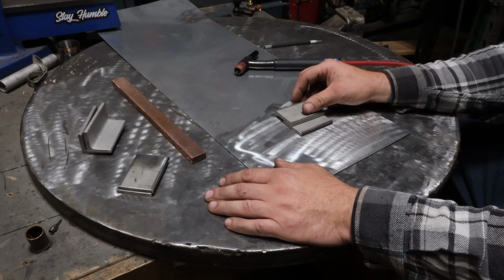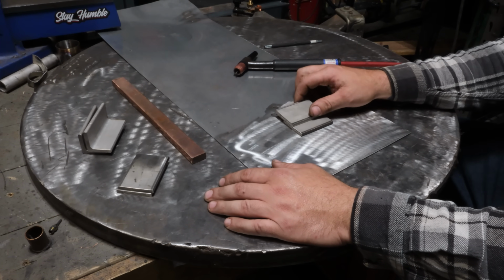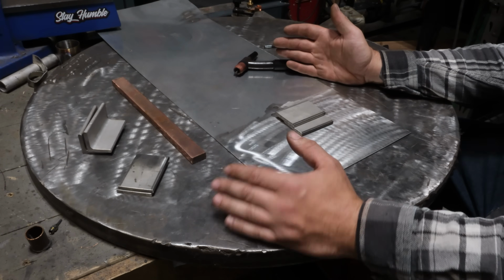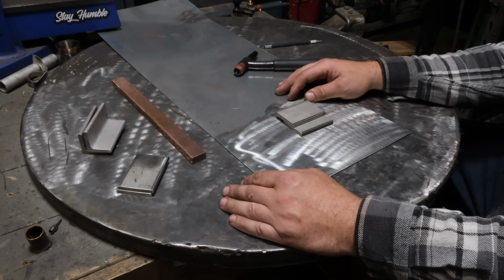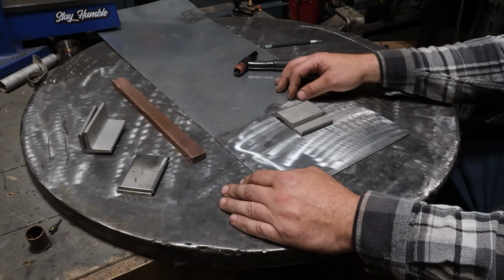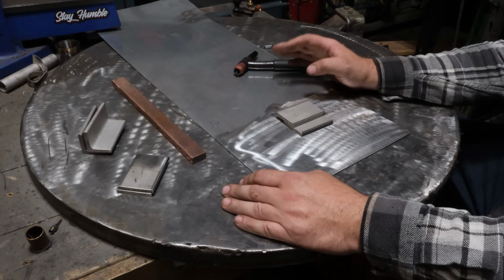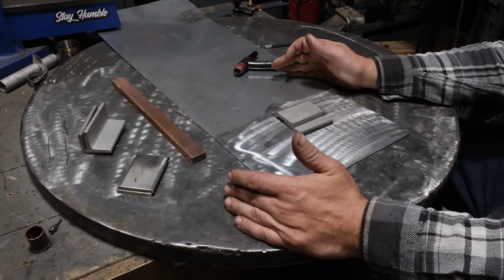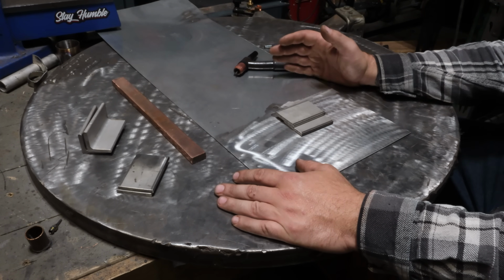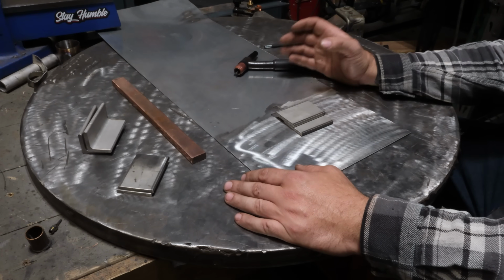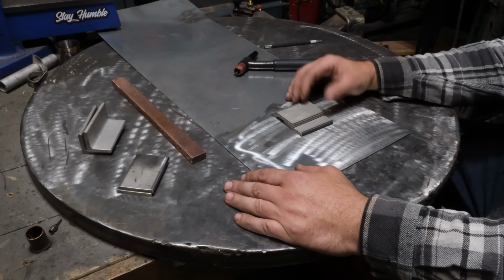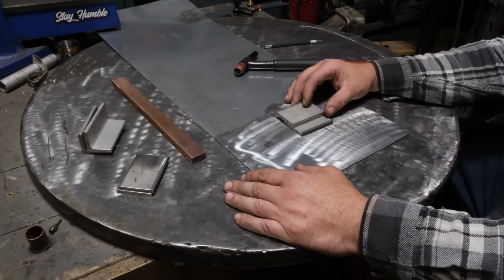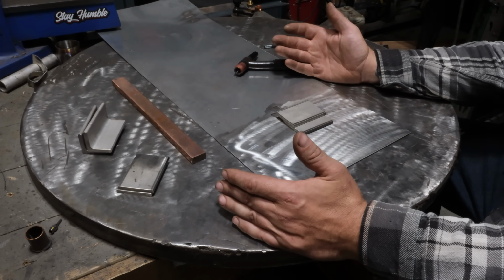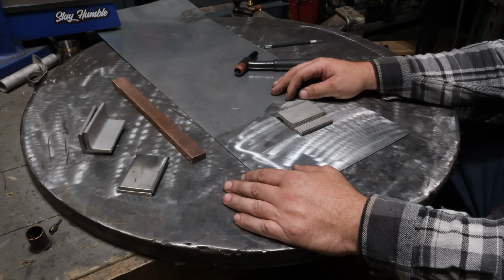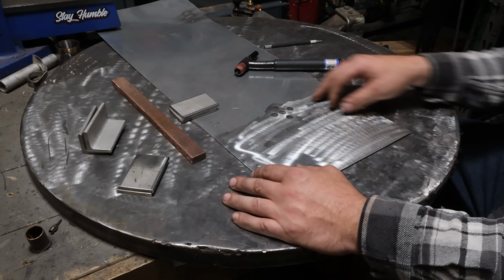For lap welds, generally speaking, you can get very good results. Same thing with fillet welds with a smaller cup. Honestly, it's probably always best to err on the side of caution. I generally weld most of my stainless with a number 10 cup, maybe a number 12. I tend not to use bigger cups than that simply because the argon coverage isn't necessarily better, and oxides on the surface aren't really a defect until you really get into that dull gray cooked. And this stuff simply isn't like titanium, where the oxide layer is a demonstration of basically material failure. Stainless is not in the same ballpark as titanium.